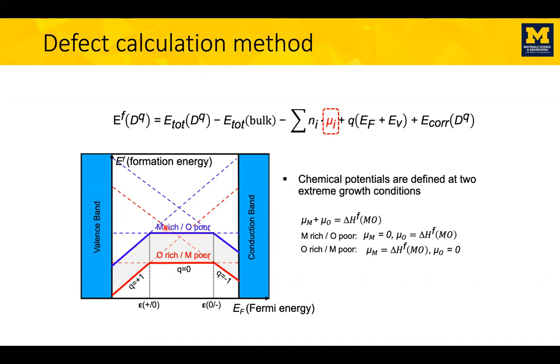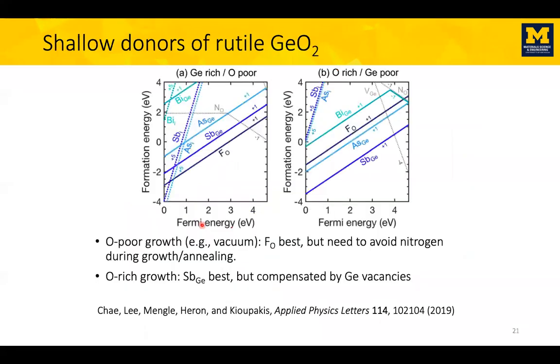Okay, and the range of chemical potentials is given by the formation energy of all possible compounds in the phase diagram that we're working with. So you see here how the environment determines the formation of those defects as well. So we have some control over forming those defects. With that, I want to summarize, because you will see lots of these plots in the remainder of the talk, and I want to make sure that everybody's following what this diagram means.